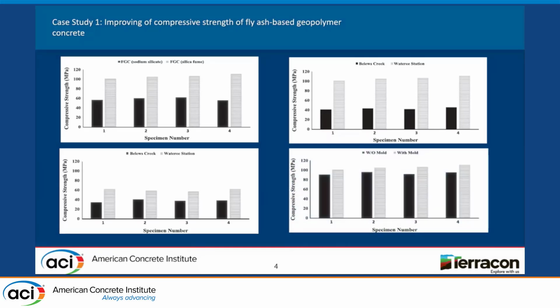Then I wanted to see the effect of the curing. Generally, when we make this concrete, I mix the activating solution a day ahead, and then we mix it with the dry material, which is fly ash, sand, and aggregate, and we keep it in the mold for 28 days. We subject it to 24 hours of external heat at 70 Celsius, 158 Fahrenheit. You can see here the result is the same as what we got, 116, which is 16,000 psi. However, I wanted to see the effect of removing the mold after we finish the curing, which is after 24 hours, and you can see here there is no effect.